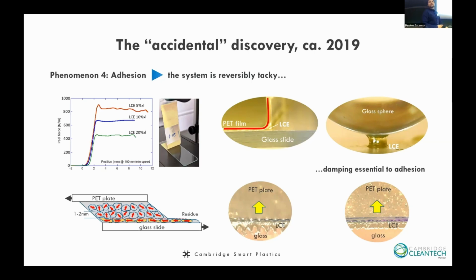And there's been a lot of research and thinking about that lately, and this is the soft elasticity at work again at the bottom. Actually, when it delaminates, if you look very closely, it's transparent on the surface. So as we're pulling it, you do cause the alignment on the surface of the domains, which then restricts it, kills your damping, boom, let's go.